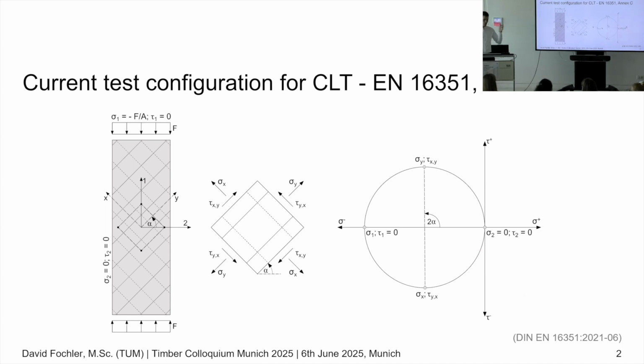But no known method yet is suitable for testing all variations of wooden elements. They are all limited to specific products. Even this diaphragm shear test setup has one problem. The resulting stress state, it's shown here, is always under compression because of the force. Here and here, we have always compression. That means if we use any other angle in the laminated timber than 90 degrees, this will result in stability failures instead of shear failure, and we don't want that.